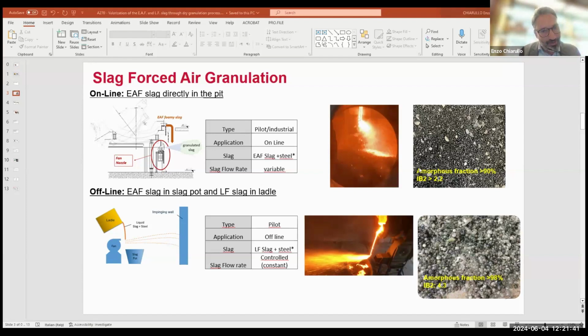Here you have the fan nozzle below the reactor. From the reactor, we have the pouring of the foamy and liquid slag, which impacts on the blowing air, performing the slag granulation. This technology was developed at industrial pilot scale for the slag treatment obtained in the electric arc furnace. Here is an example of the powder that we obtained, which has an amorphous fraction of approximately 90% with a basicity index of more than 2.2.